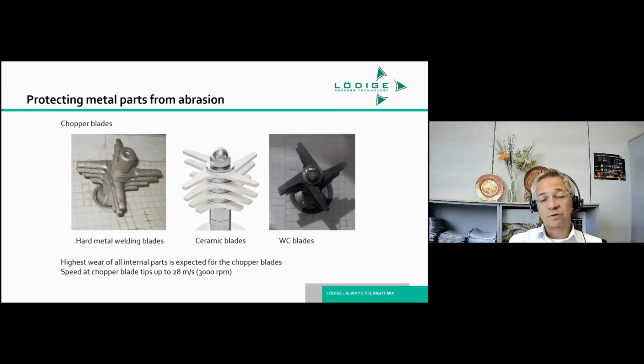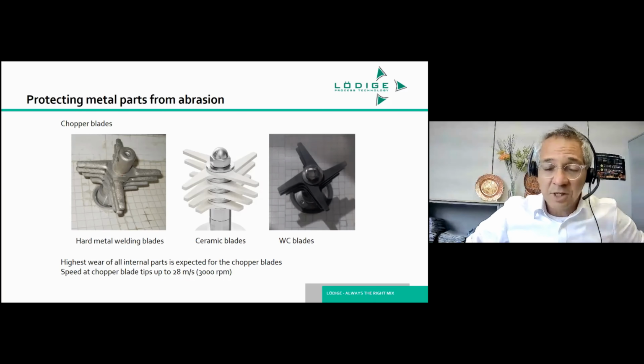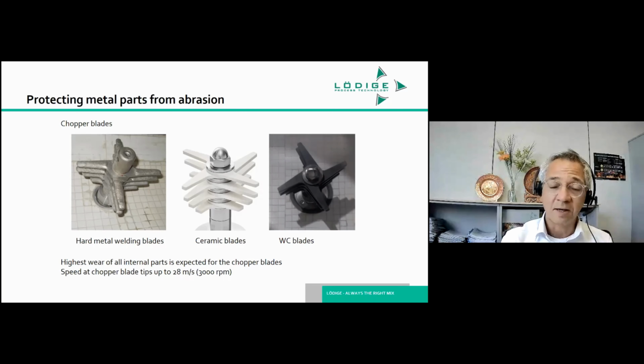So alternatives were sought. And one idea was to make the blades from materials which are abrasion resistant, but do not contaminate the mix. So the blades were made either of ceramic, so it's very hard, or from the tungsten carbide material. Again, very hard, very, very abrasion resistant. And since the chopper blades operate at 28 meters per second tip speed, this seemed to be a very good option. And this has more or less established itself as one of the key features of a mixer, apart from coating the mixing elements and the shaft or the drum.